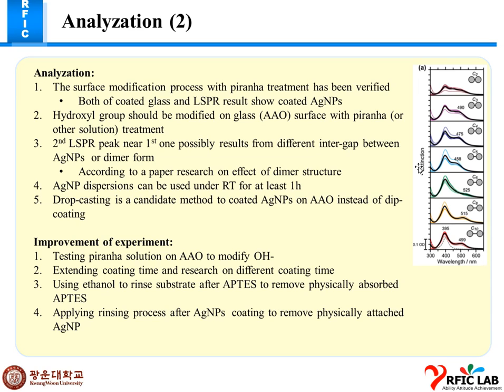because the Ag nanoparticles are basically just particles. If we put them onto the glass with dip coating, it is not the appropriate method, as we have checked through the LSPR. But drop casting is a favorable method compared to dip coating. So the improvements in this experiment are testing piranha solution on AAO to modify OH, extending the coating time and researching different coating times, because we have to check at what time we get the coating on the surface, using ethanol every time to rinse the substrate after APTES to remove physically adsorbed APTES, and applying rinsing to the coating to remove physically attached AgNPs.